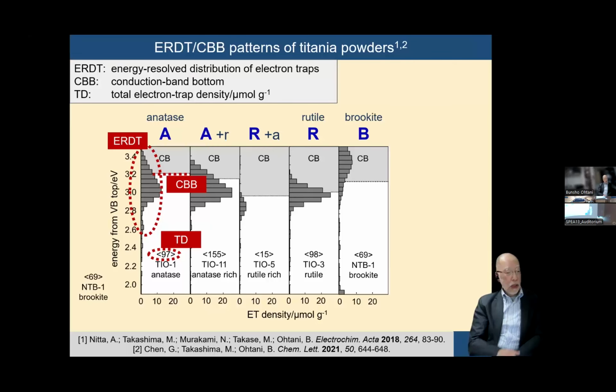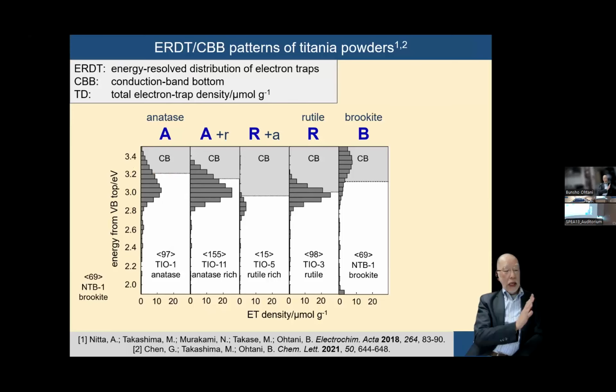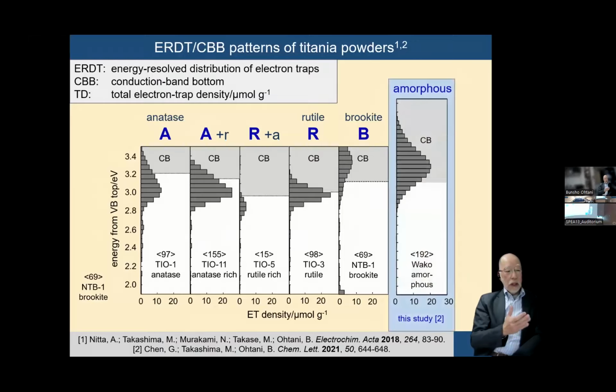All these patterns contain ERDT, CBB, and TD, at least three parameters. There are anatase, anatase with a small amount of rutile, rutile with a small amount of anatase, and rutile and brookite. And the pattern seems to depend on the crystalline structure. However, the amorphous sample, completely amorphous but with TiO2 composition and no XRD peak, also shows a similar pattern, but at a bit higher energy. So not only crystalline but also amorphous samples show this.